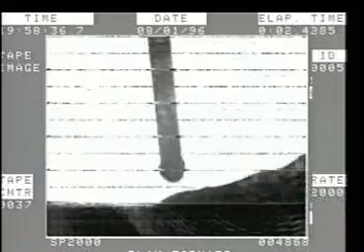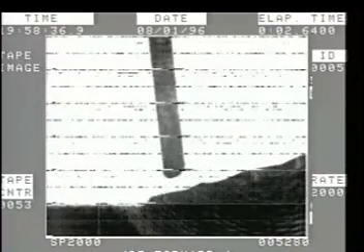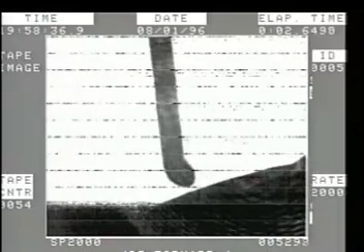By using high-speed photography, you can actually see droplets forming on the end of the electrode. Current is applied, the droplet is pinched off, and transferred into the puddle. Spatter occurs when the shorting is not done perfectly or there is interference to the puddle. Spatter balls can pop out of the very violent puddle as it oscillates.